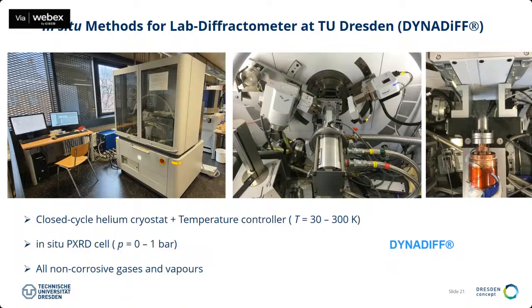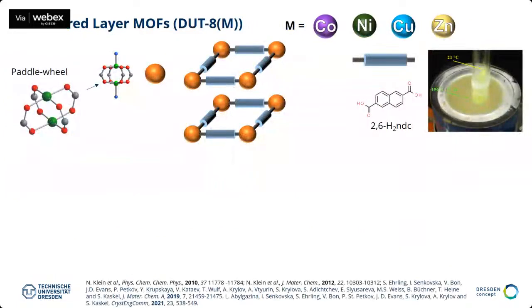This is really a workhorse nowadays, because here you can measure a full adsorption isotherm on your sample. This is an enabling tool, and at the same time you can measure the powder XRD patterns that allow you to analyze what is going on in the structure.